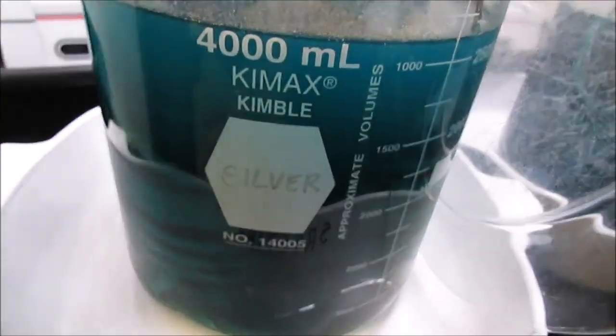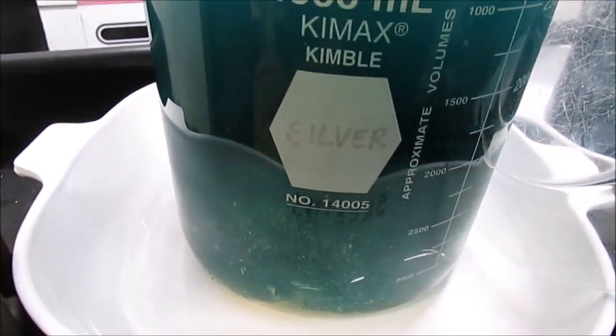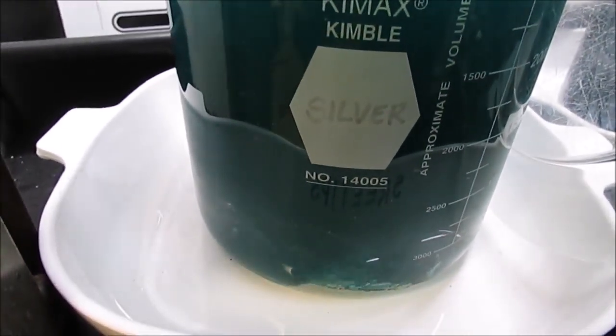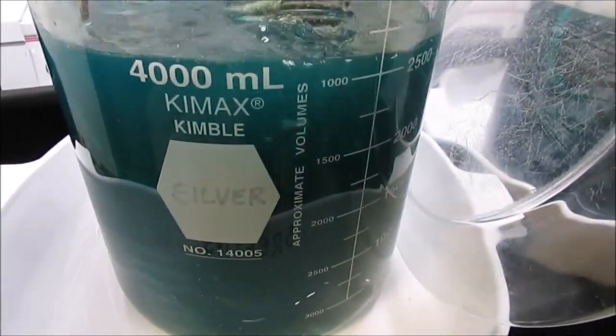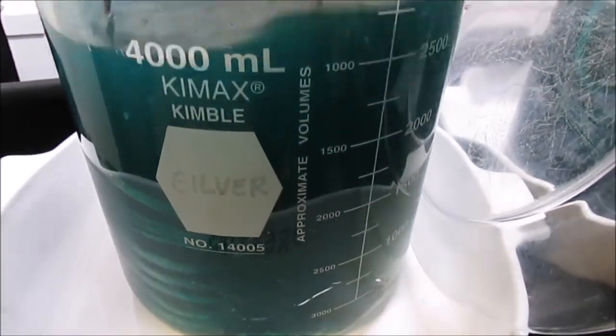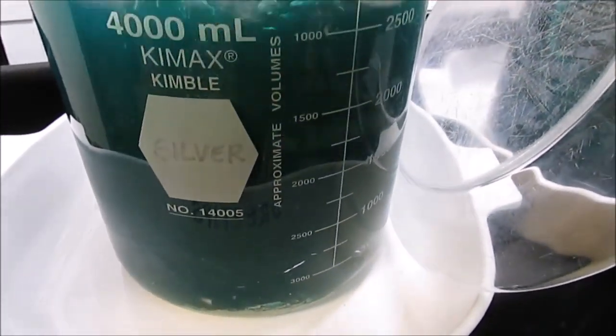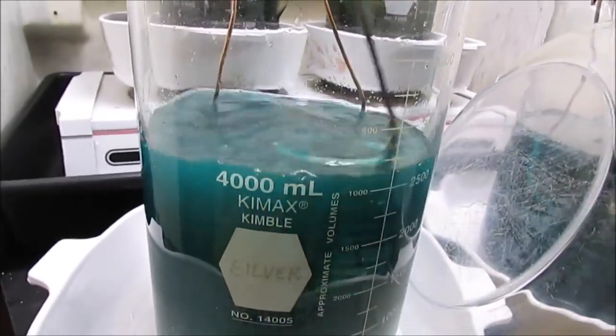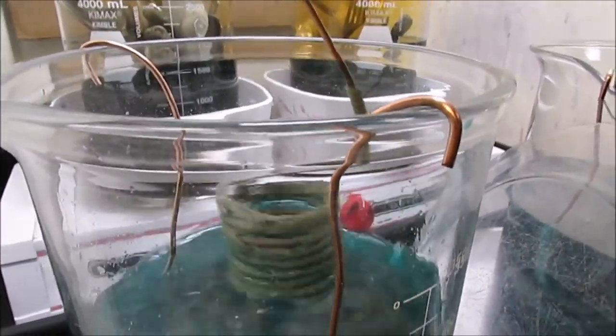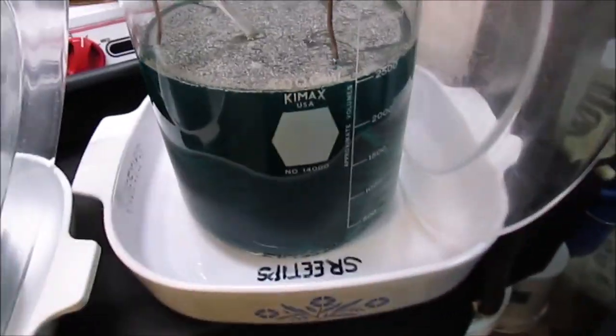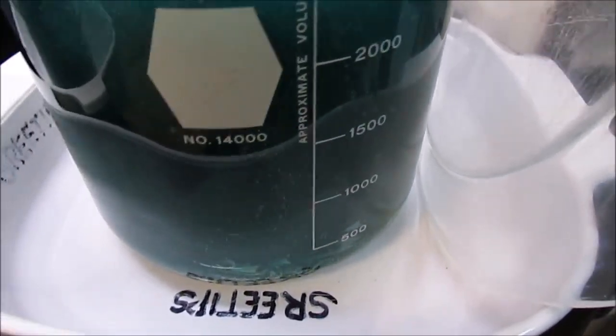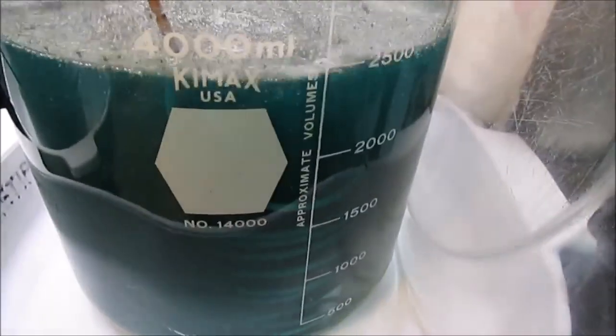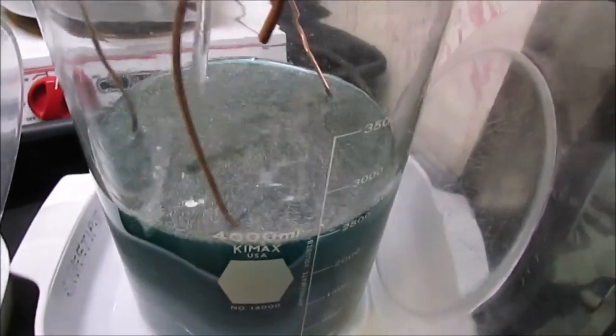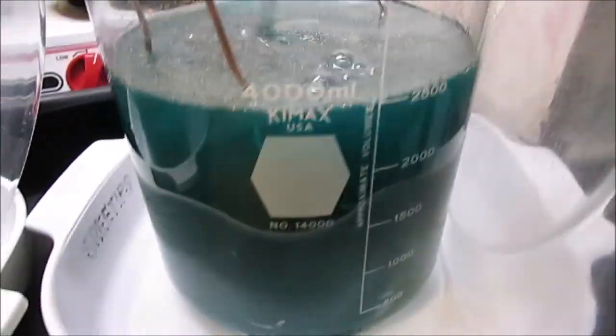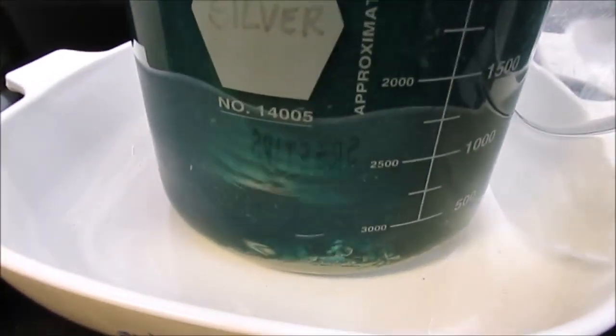Okay, if you take a look at this silver here, it's cementing out nicely onto the copper. I don't have any fumes forming or a bunch of silver floating to the top, which is something you want to try to avoid. If we had excess nitric acid in here, the copper would be dissolving, the solutions would be heating up, and we'd have a bunch of fumes coming off of this. But we don't see that in here, and that's a good thing. That's what we want when we do the cementation process.